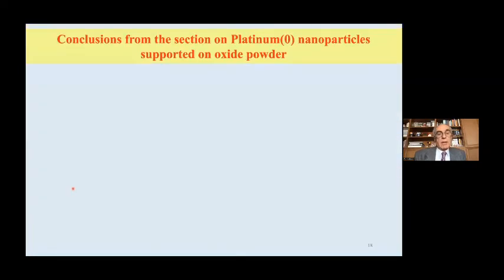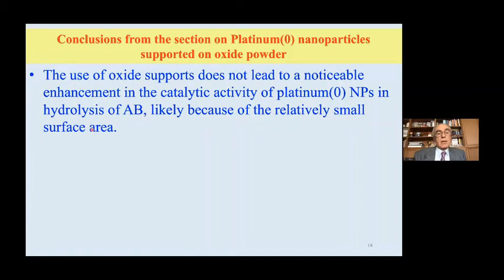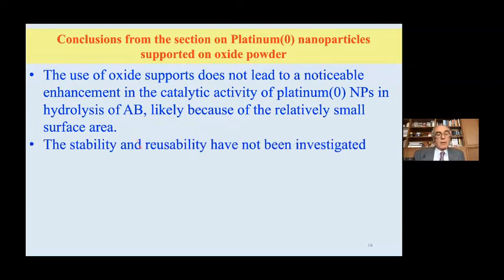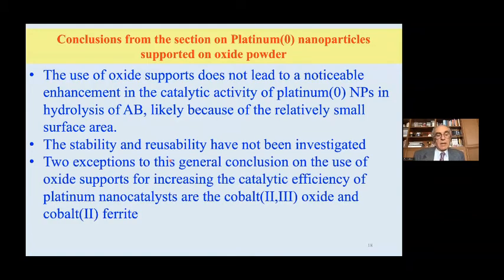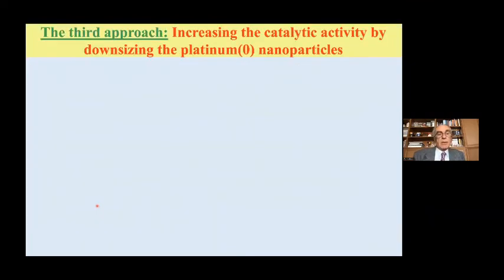However, the use of oxide support does not lead to a noticeable enhancement in the catalytic activity of platinum nanoparticles in hydrolysis of ammonia borane, probably because of the relatively small surface area. The stability and reusability have never been investigated. There are two exceptions to this generalization. One is the cobalt 2,3 oxide, cobalt oxide, and the other one is the cobalt ferrite. I will talk about that in a minute.